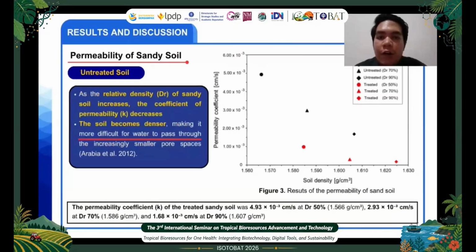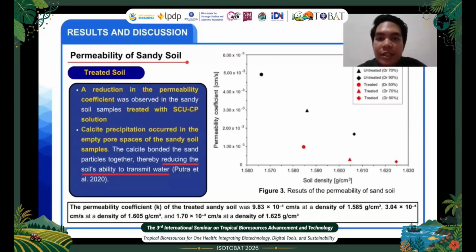For the untreated sand, the coefficient of permeability decreases with increasing relative density. This is because higher density results in reduced pore space, which restricts water movement through the soil. In the SCU-CP treated sand, a significant reduction in the permeability coefficient was observed. Calcite formed within the pore space and bonded the sand particles together.